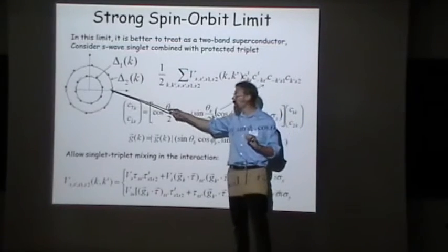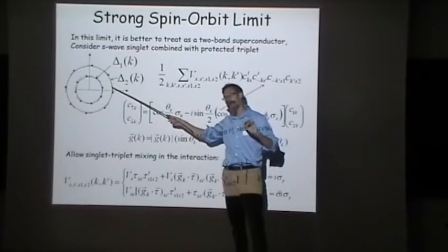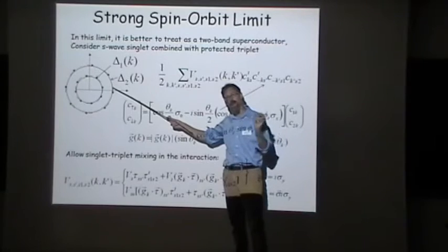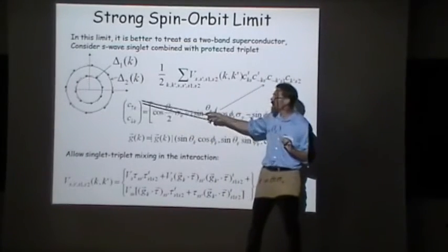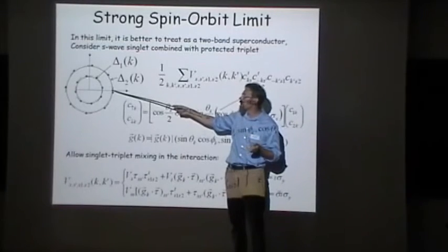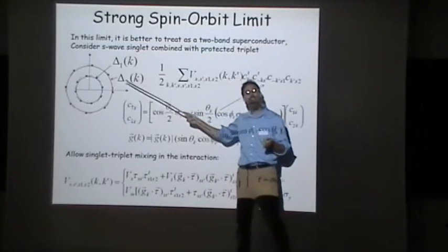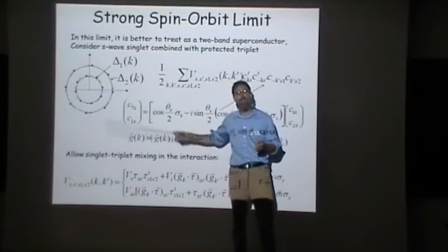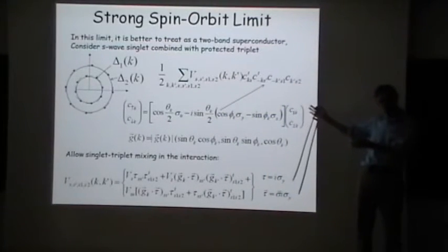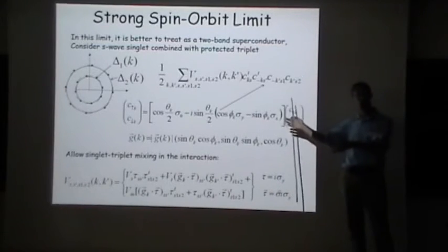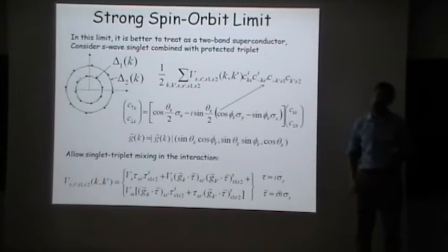So we have a single band, in principle, some sort of band function, which has some band dispersion. We haven't specified what that is. But because the spin-orbit coupling breaks the twofold degeneracy into two different spin channels, the two bands here do come from spin. So we don't need to worry so much about the orbital part. We're really focusing on the spin part. But you're right, in principle you should consider it.